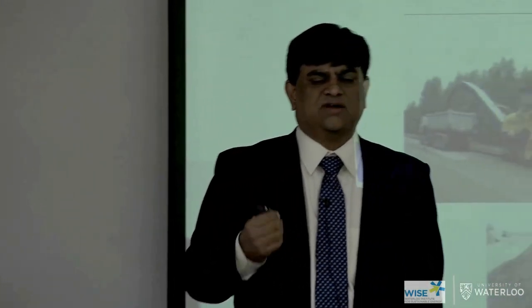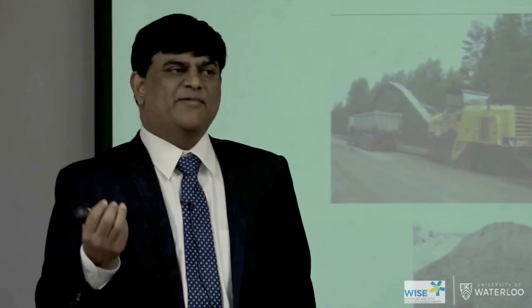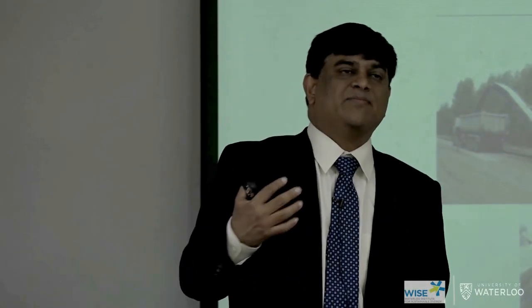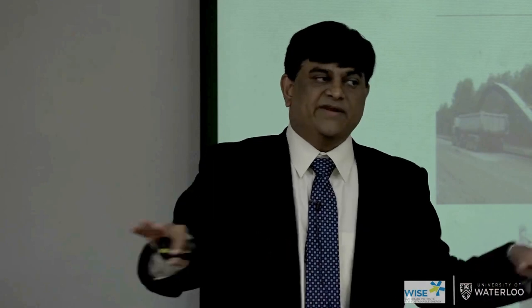This aggregate, I had sometimes some issues. In some projects, when we used the old concrete aggregate or old cement concrete aggregates, what happened is this aggregate already has cement, so it has calcium. In one particular project, it didn't work. What happened is we put the aggregate as a base material. Underneath that base material, we had sulfate soil. We didn't realize that, okay?